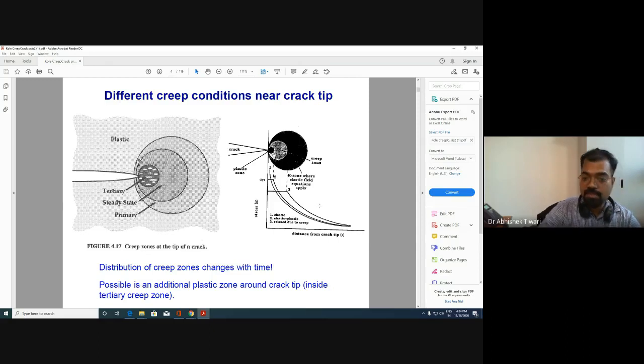But you see that the stress increases as you go close to the crack tip. In this plot on the right hand side, you have a crack tip at this point, okay? And the x-axis here is the distance from the crack tip. Zero means you are exactly at the crack tip. As you go to the right on this axis, you are going away from the crack tip. If you go much further away, then the stresses are equal to what you have applied, and obviously they are elastic. As you come closer to the crack tip, the stresses are increasing.